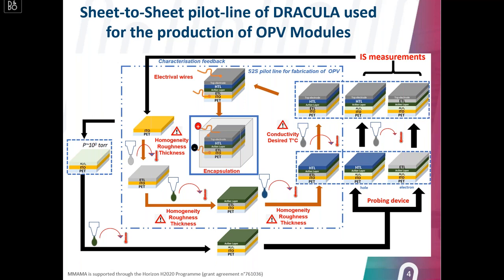Our process today is composed of different steps, but the main one is printing the different layers. In order to guarantee the performance as well as the stability of our modules, we should have good control of the different printed layers, which number from 3 to 4. Then for each one, we have to do a post-treatment in order to anneal the solvent and obtain thin films. These thin films should be homogeneous, the roughness should be very low, and the thickness should be well controlled in order to guarantee good performance.